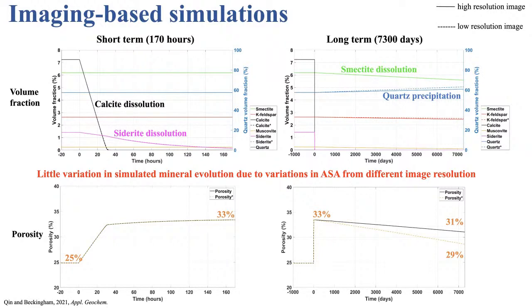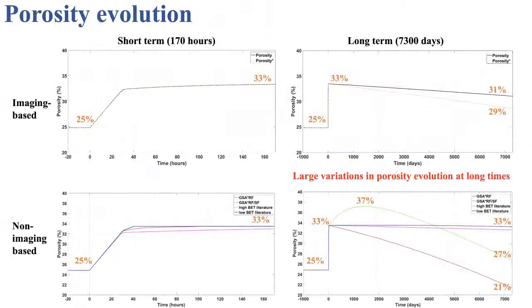If we now compare that with the simulation results using the other surface area approximations, we're just going to look at porosity. Here on the short time scale, we see that they agree relatively well with each other, predicting increases in porosity that are pretty similar. But over longer time scales, we can see we have a lot of variation. So in some cases you have further enhancements in porosity and then much more drastic reductions in porosity over time.